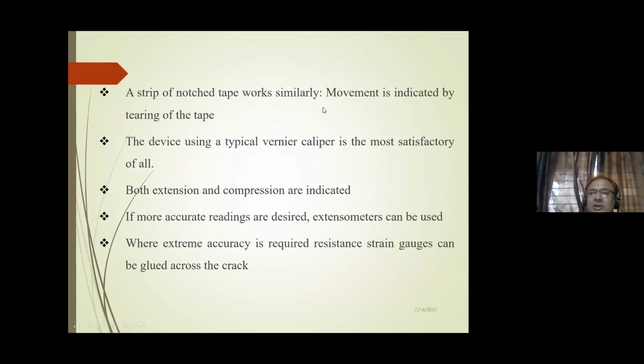Strip of notch tape works similarly. We have to tape on that particular crack. If there is tearing of the tape, then there is movement. Then a device using a typical vernier caliper is most satisfactory of all. We can measure that crack by the vernier caliper and know the extent of the crack and the seriousness of the crack, whether it is live or dormant. Both extension and compression are indicated. We can use the strain gauge also. If more accurate readings are desired, an extensometer can be used. Where extreme accuracy is required, use a resistance strain gauge. I told you that if you want extreme accuracy, the strain gauge can be glued across the crack and we can get the result.